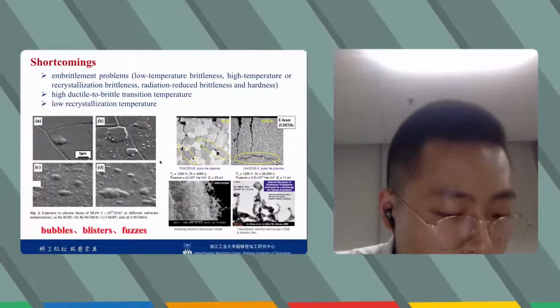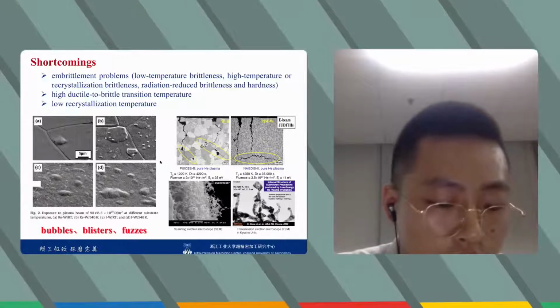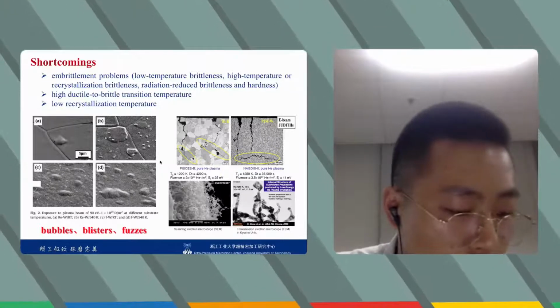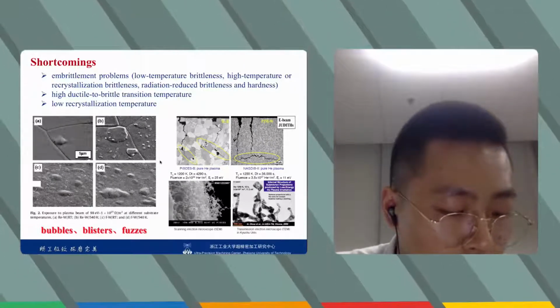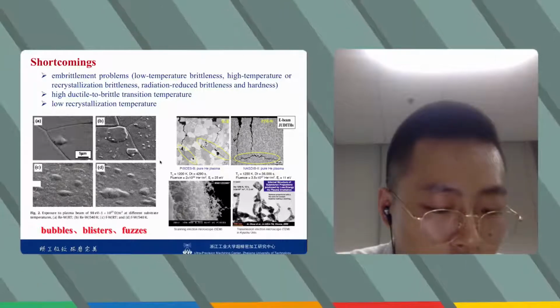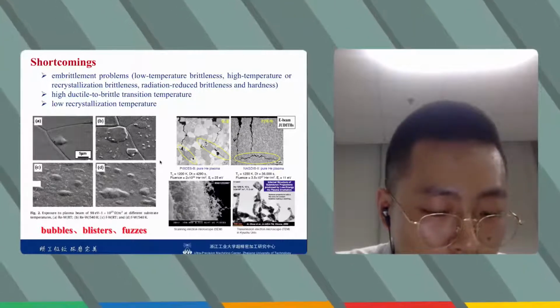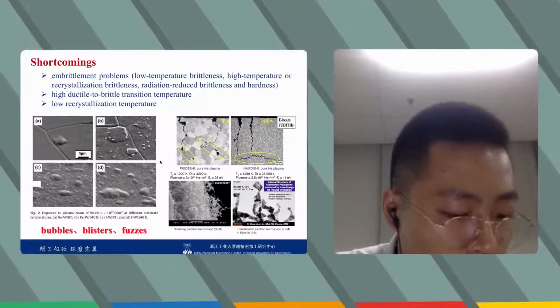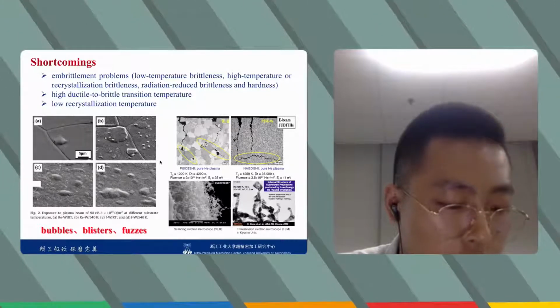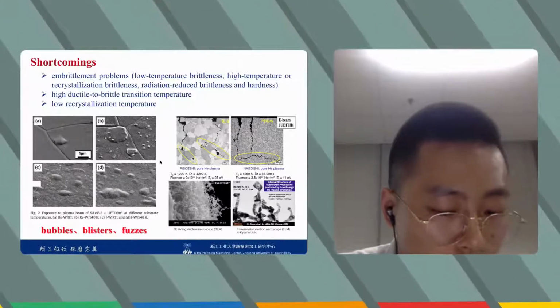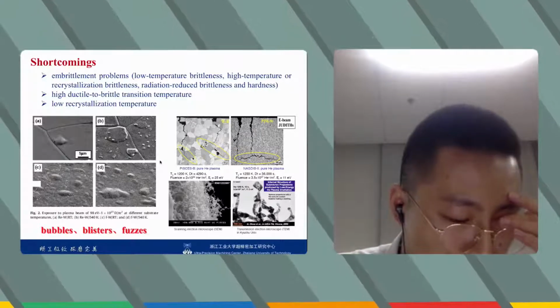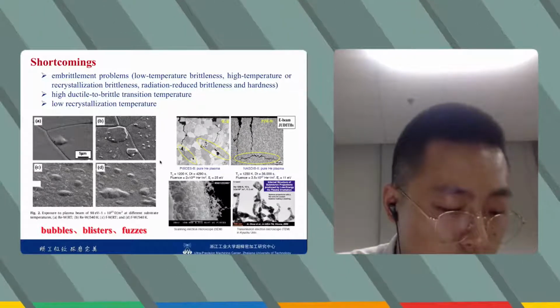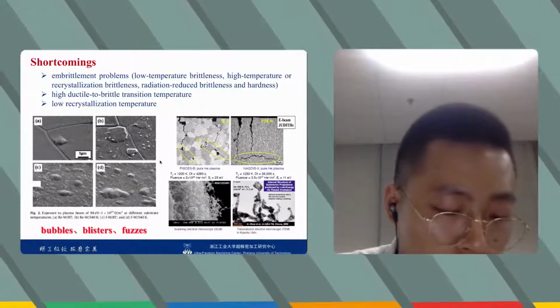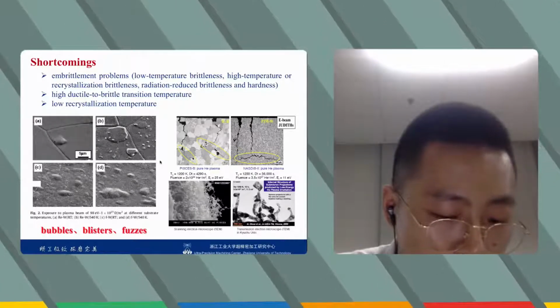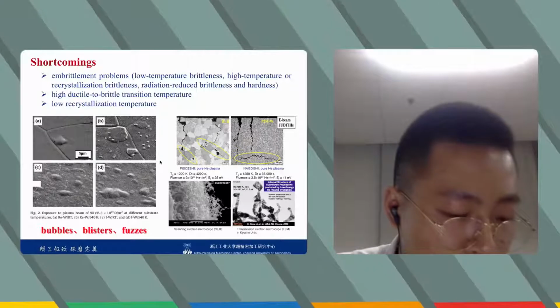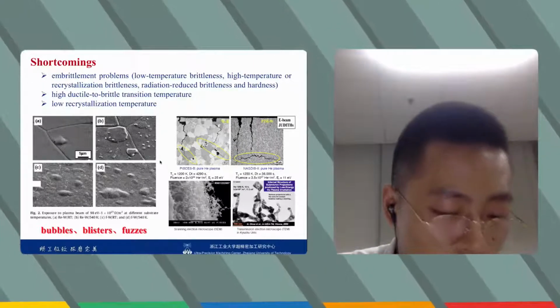The surface of tungsten will be directly exposed to high energy particles such as hydrogen and helium, leading to bubbles, blisters, holes, and even fuzz. This irradiation damage degrades the thermal and mechanical properties of the material surface, shortens the lifetime of components, and ultimately impacts the reliability of the fusion reactor.